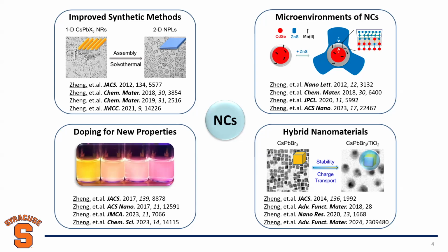For example, perovskite materials have very limited stability, even though they are green materials with many excellent properties that I'm going to show you in my talk today. But they have limited stability. So what we did is we developed an oxide shell coating method. We shell with titanium dioxide. We enhance the stability, and also we improve the charge transport properties for photocatalytic reactions. So here you can see the big picture of our research. In the next 15 minutes, we will try to touch on each of them with one example.